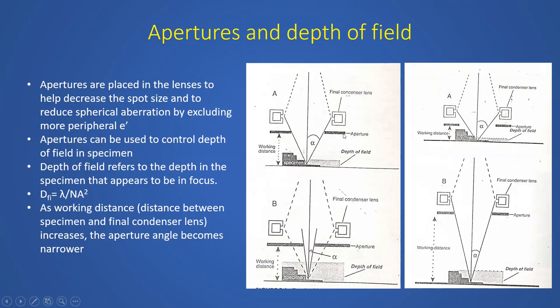Right here you can see that the aperture is wide. It's a wide aperture here. And if you close this aperture, this is a smaller aperture, you can increase the depth of field, which is the height of the sample that you can have in focus, which is something you want. So by decreasing the size of the aperture, you can get this. Also, by increasing the working distance, you can achieve this. This is a semi-angular aperture, this is the alpha here. So you can reduce this.